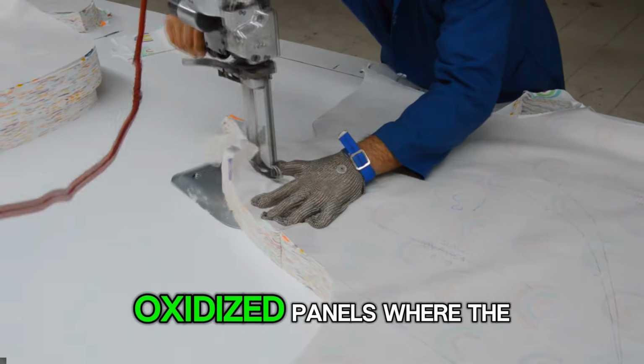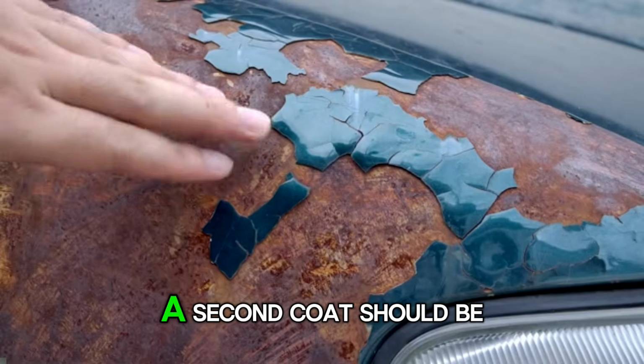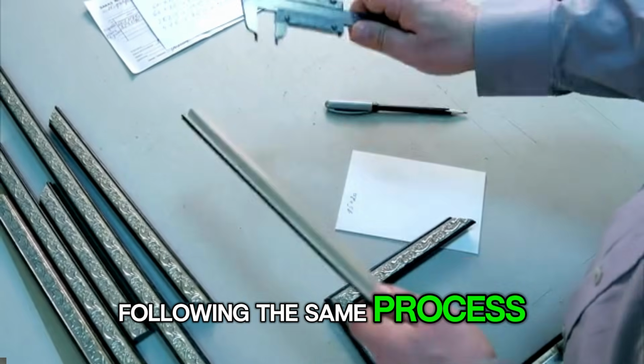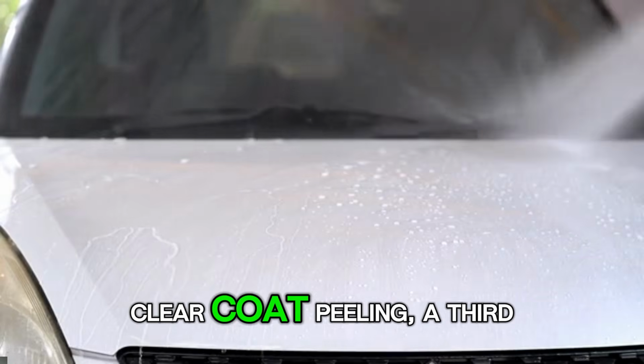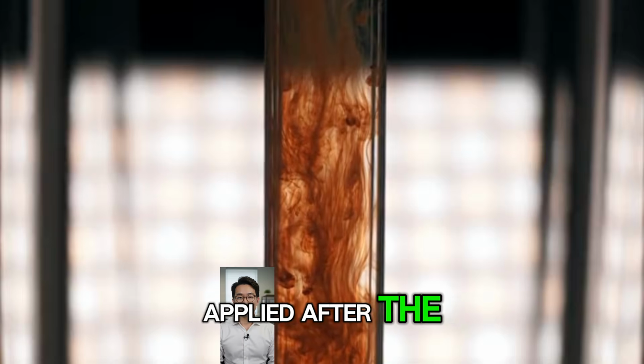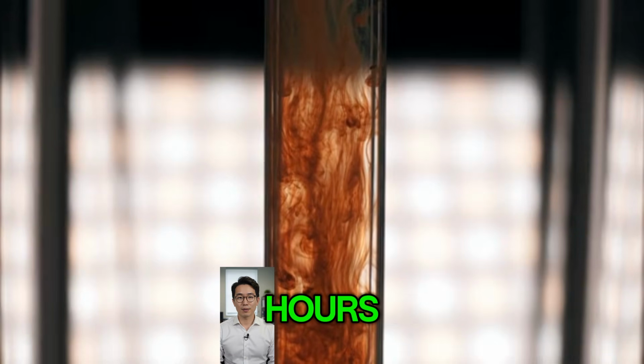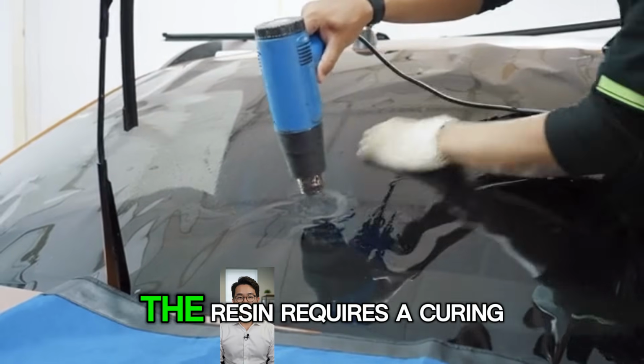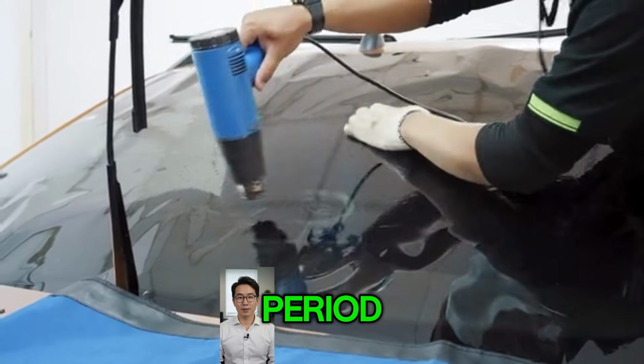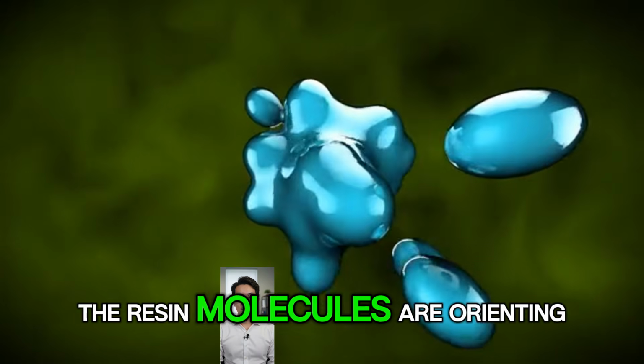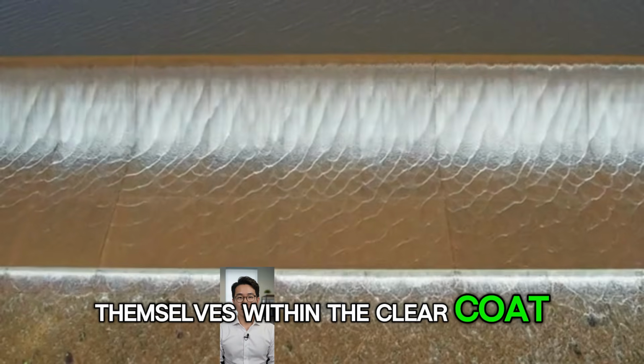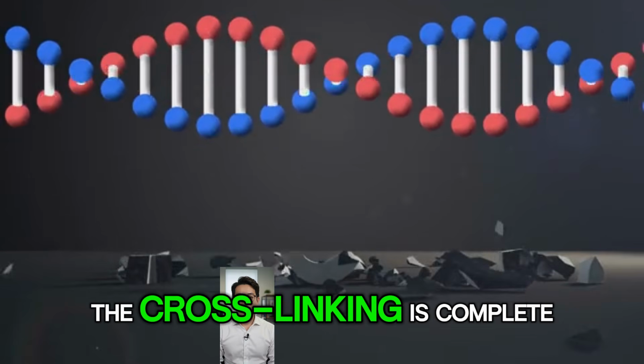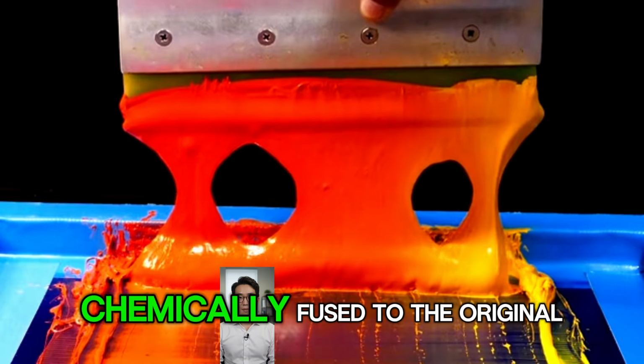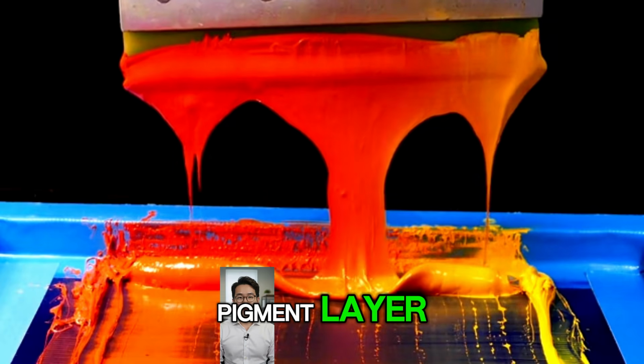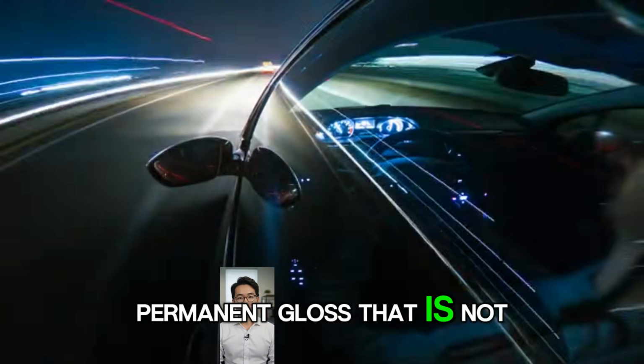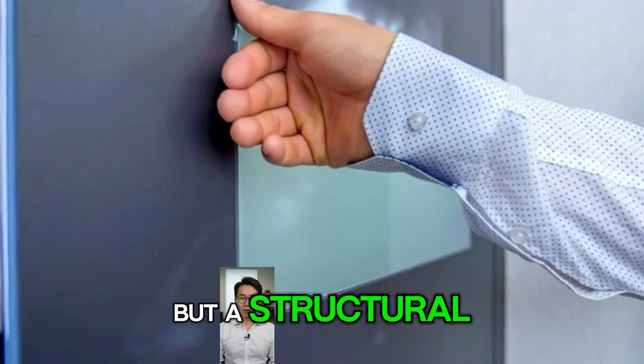For severely oxidized panels where the paint is heavily chalked, a second coat should be applied following the same process. For vehicles with visible clear coat peeling, a third coat can be applied after the second has cured for 24 hours. After the final application, the resin requires a curing period. For the first 12 hours, the resin molecules are orienting themselves within the clear coat. By 48 hours, the cross-linking is complete, and the resin is chemically fused to the original pigment layer. The result is a deep, permanent gloss that is not just a coating sitting on top, but a structural restoration of the paint itself.